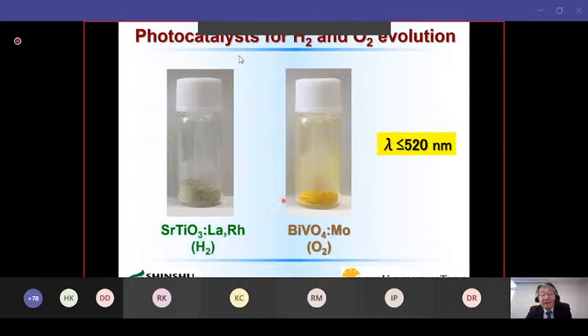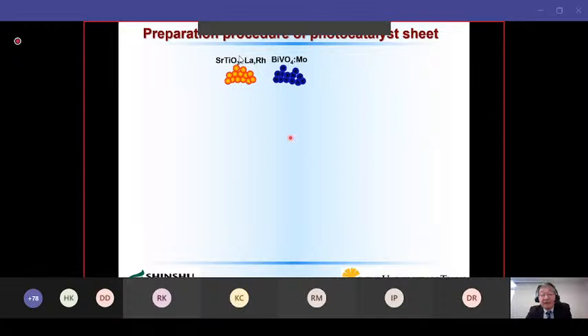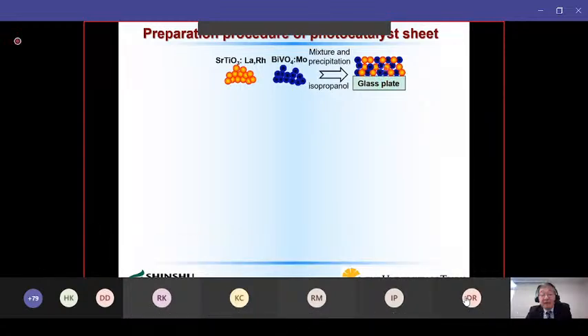The color is a little bit different, but if we observe by UV diffuse reflectance spectroscopy, the absorption edge in both cases extends to about 520 nanometers. Then the preparation procedure is shown here. We mix these two particles in an isopropanol solution, then just drop cast on a glass plate. Then after drying, we get this kind of mixed particle layer. The thickness is at most about 10 micrometers.